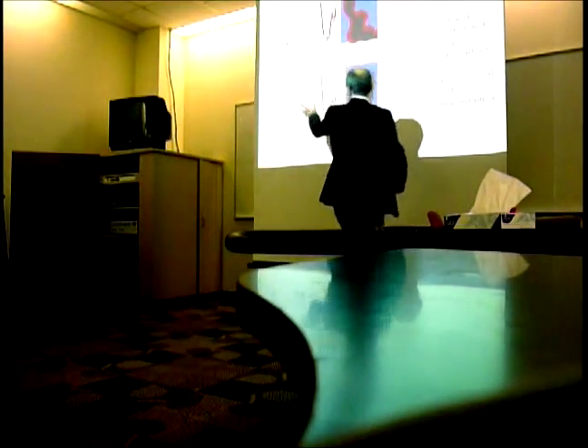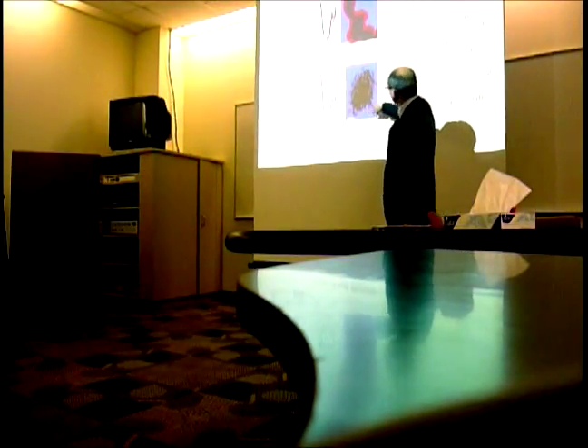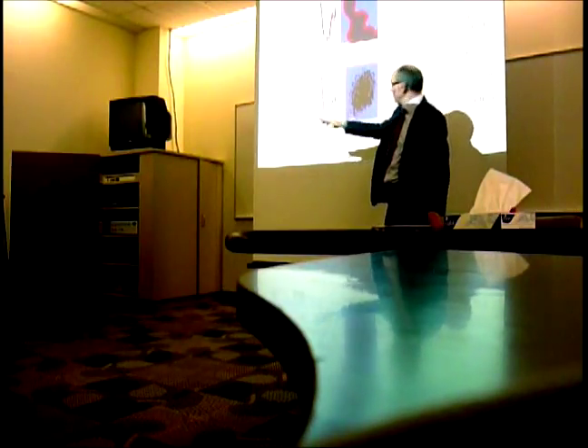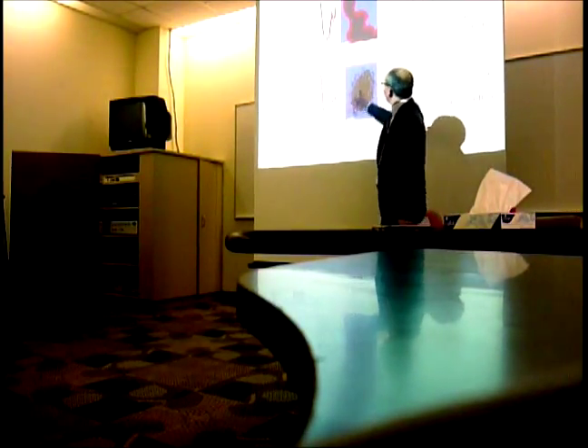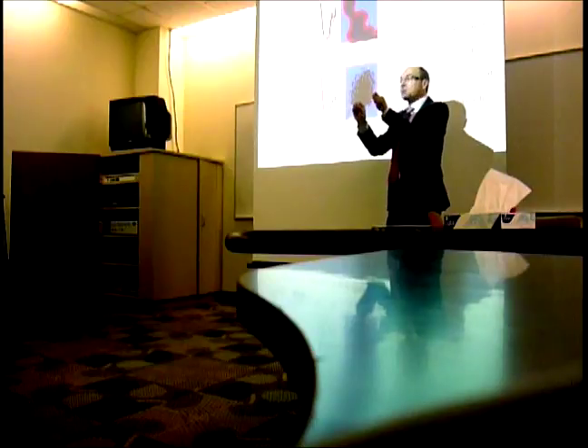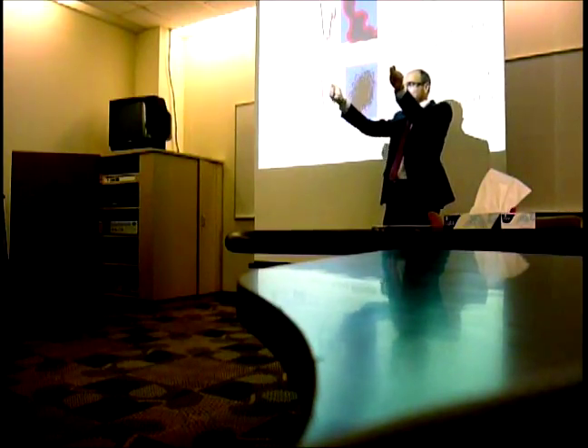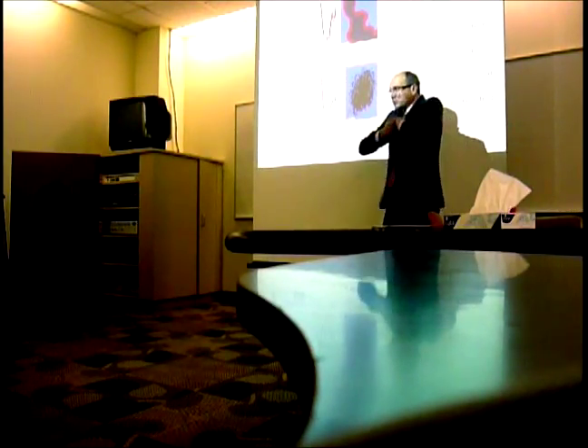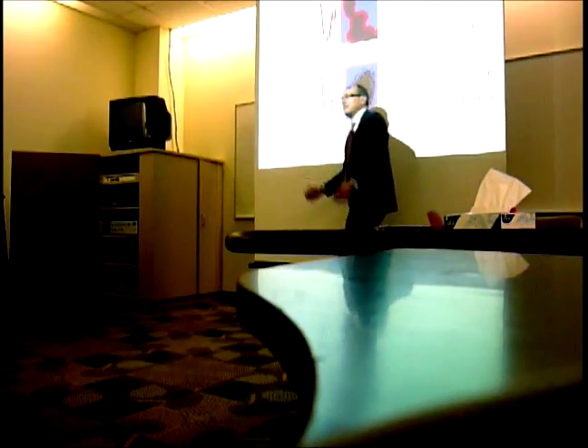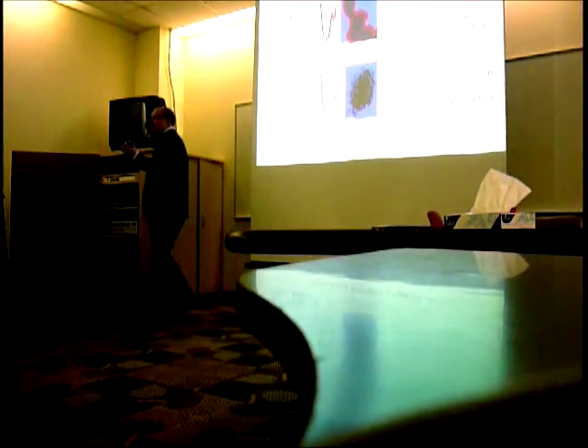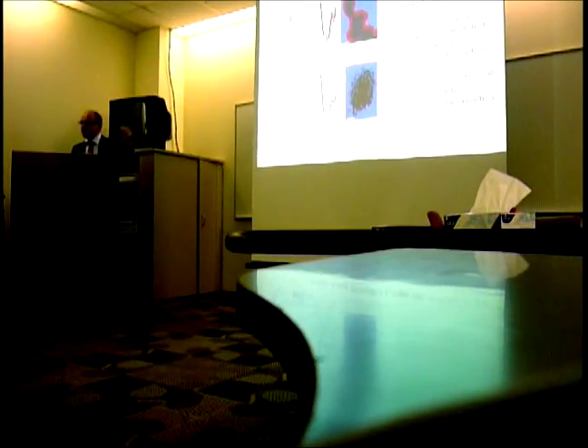So we can do this. We can measure X-ray microscopy, and here I show you the coating. These are the spectra, the carbon spectra, and here I show you the catalyst which continues to work. And this is a picture of the catalyst which deactivates fast, and after a while that red is a coat. It's a coat around the crystal. So we can now understand at the local level why things are deactivating, why things are, for example, working better or worse.